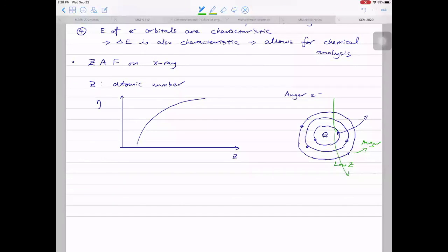Okay, great. Then after that, what I mentioned was the Auger electrons, talking about why for low Z elements we don't get X-ray. Assuming we knock out electrons, where did the energy go if it's not emitted as X-ray? The first reason is the competition between Auger electrons and the characteristic X-ray. For low Z elements, after knocking out the electron, it leaves a hole.